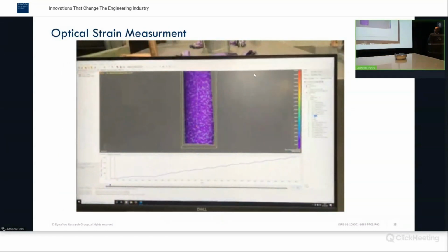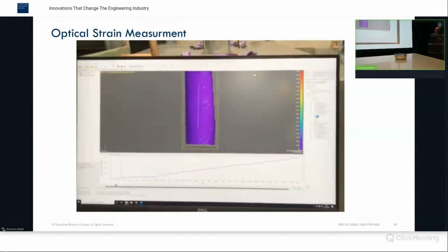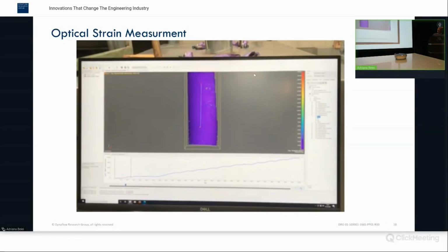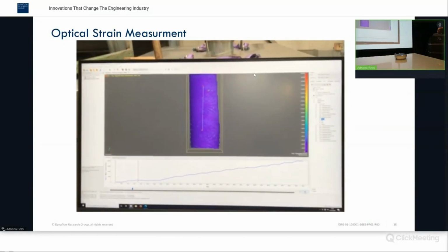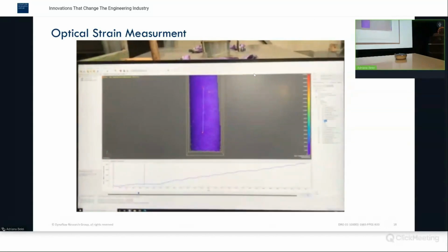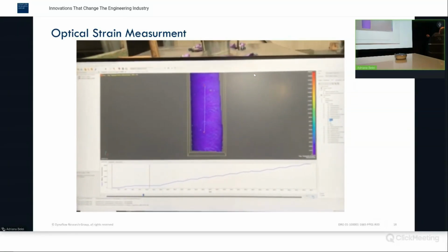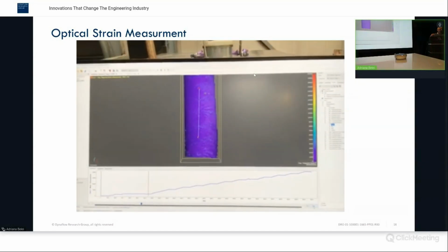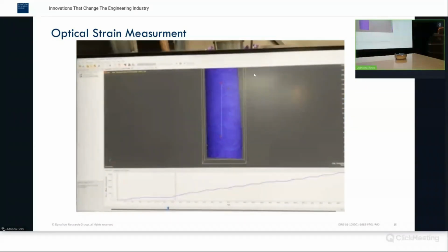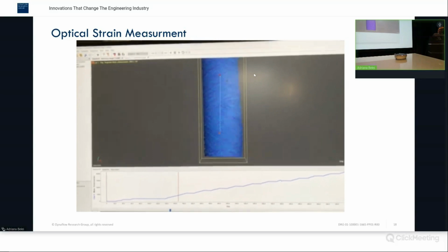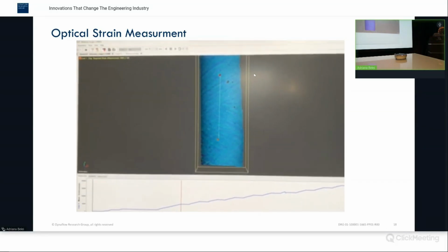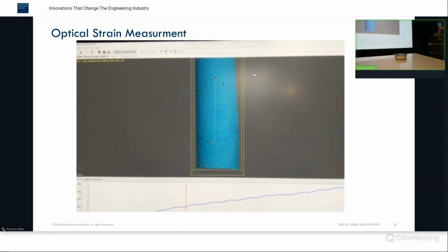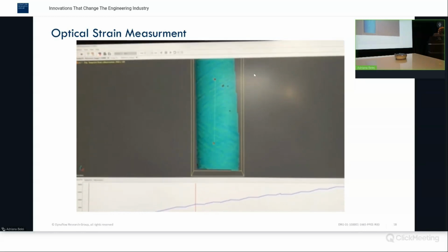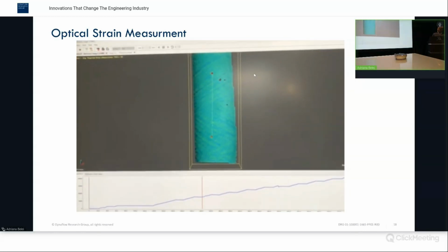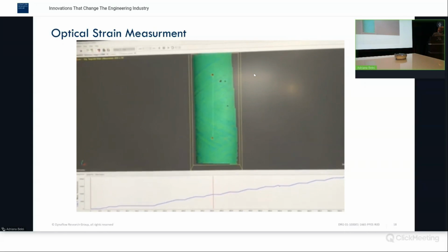So this is a picture of the optical strain measurement. You see a vertical line drawn here. That is the line where the strain is measured. And you gradually see the development of cracks in the system. During what test? This is during an internal pressure test.